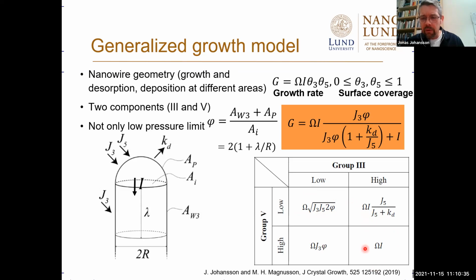But the most relevant for these experiments, that is high group 5 and also high group 3. And then you see we are in a saturated growth regime. Growth rate depends only on temperature, because this is a rate coefficient, and the surface coverages are essentially 1. So it's saturated growth, not pressure dependent, not diameter dependent. So I think this is how we can understand the growth rate dependencies of Aerotaxy growth.